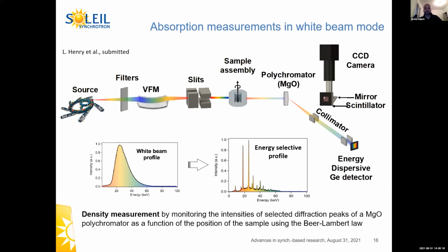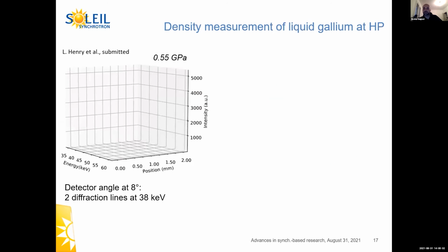And then the density measurements can be done by monitoring the intensities of selected diffraction peaks of that polychromator as a function of the position of the sample, using the Beer-Lambert law as normal, just like the monochromatic beam configuration. So this is an example done by Laurent Henry, my postdoc, a density measurement of liquid gallium at high pressure.